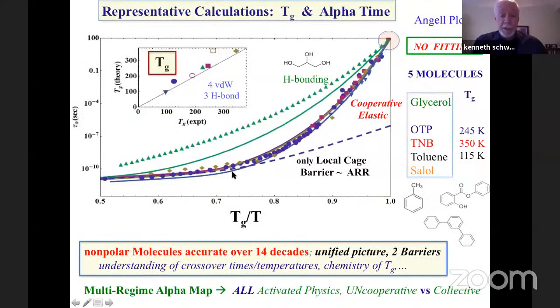I don't want to discuss it in detail. For those of you who know some chemistry, here's 5 of the molecules. What's shown here is the alpha time. Again, there's about 14 orders of magnitude. It's an Angell plot, Tg over T. There's 4 experimental systems in here. They just happen to overlap because their fragilities are similar. And there's 4 theoretical curves in there that are not fits. So of course, there's not perfect agreement, but we think the level of agreement is far better than you should ever expect. So there's no fitting.